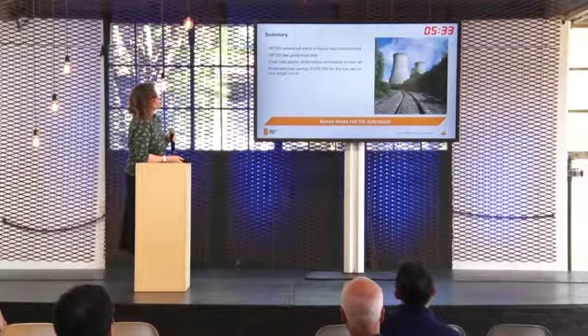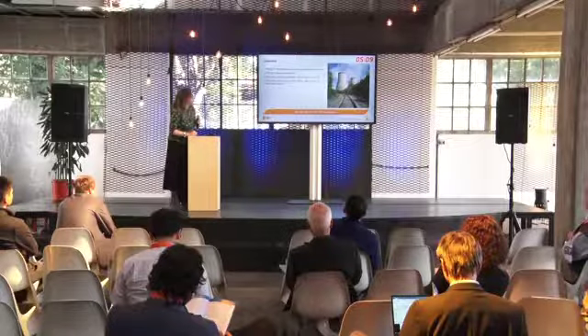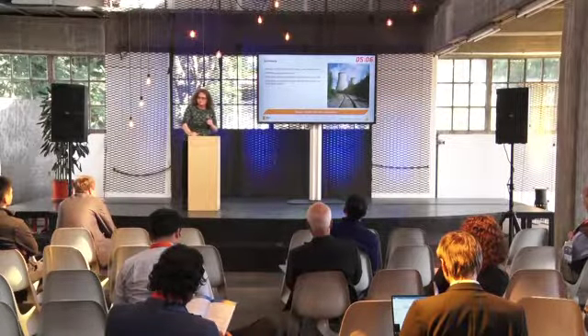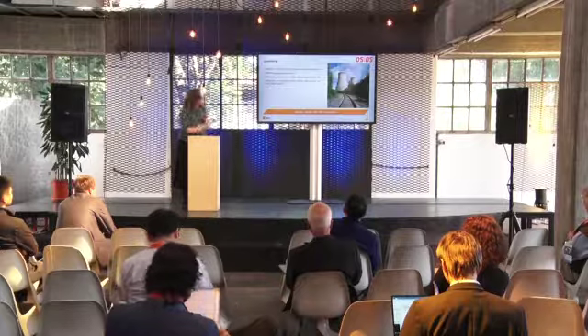So just to summarise, we've monitored HP325 within a heavy haul environment. It's performed very well, particularly in terms of the plastic flow and the crown profile retention. They do have to grind it now with a grinding regime where they didn't have before, but even in taking into account the costs of grinding, they are getting that significant life extension. And overall, around about 7 times life extension. And that's the end of the slides.